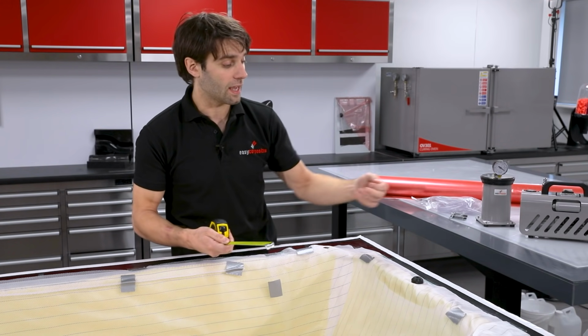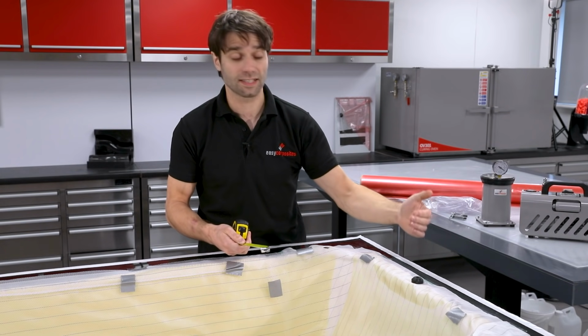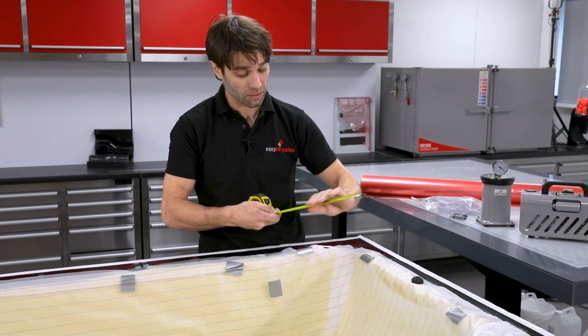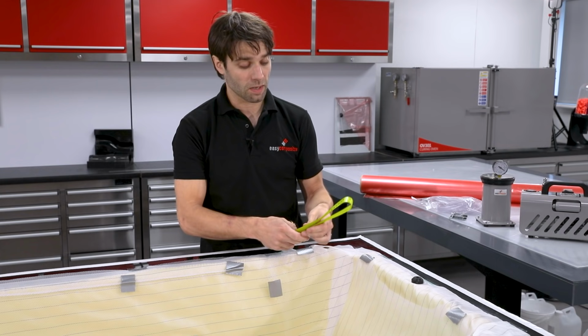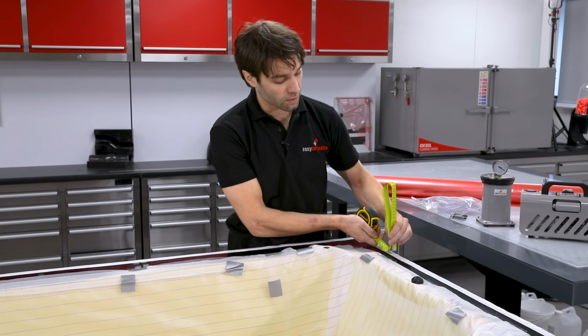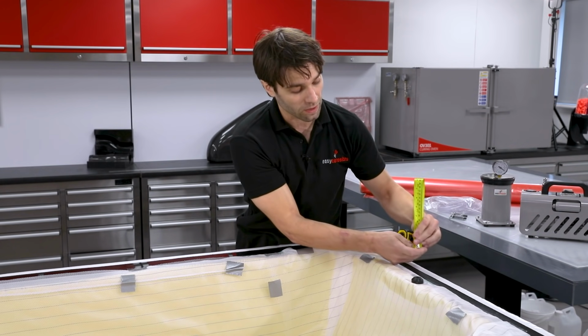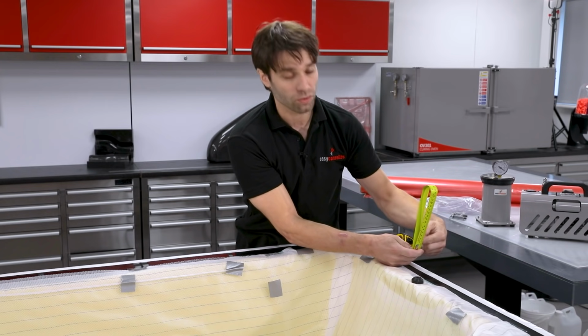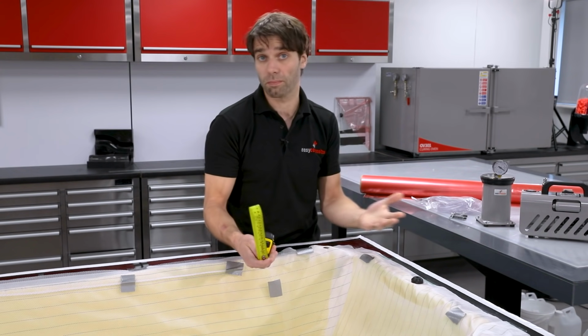The way we do that is by putting in pleats into the seal so that we have the extra bag. So to get the 800 millimetres, if we did 2 pleats that were 200 millimetres tall, that will give us the 800 millimetres. So 200, 400, and then doubled up, that's your 800 mil.